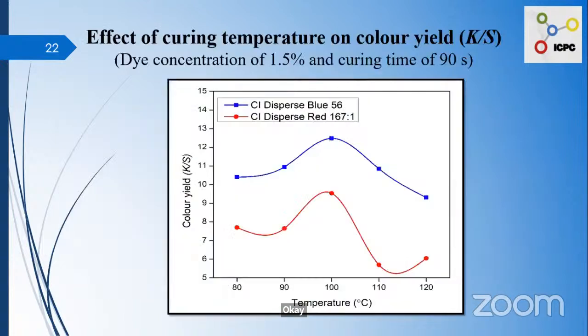This graph presents the effect of curing temperature on color yield of the dyed polyurethane nanofibrous mats with 1.5% of the dye for 90 seconds of curing. The figure shows that by gradually increasing the curing temperature, color yield improved up to 100 degrees centigrade, and afterward it started declining for both dyes. That may be due to the possible deformation of the polyurethane nanofibers after 100 degrees centigrade. The color yield of dispersed blue 56 was better than that of the dispersed red, and that may be because the lower molecular weight dye diffuses and fixes better than the high molecular weight dye.